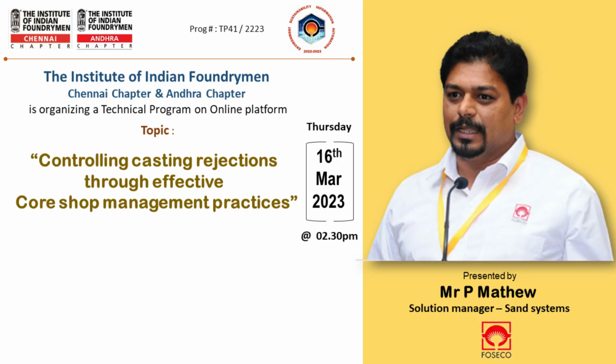How to measure SiO2 purity in sand for better refractory method? You are talking about the silica content? Correct. Okay, silica content. There are analytical methods which are a little cumbersome. You treat it with HF, basically etching with the HF, then repeat this cycle over a period of time and effectively remove the silica and then weigh it. That is the analytical method. But XRF can also give you an idea, though you have to do multiple calibrations. If you do it multiple times and establish the process with the people or laboratory doing it, then you will be able to correlate it, because XRF will not give you the exact reading. So do a couple of samples with both XRF and the analytical HF method, then you can correlate a relation.